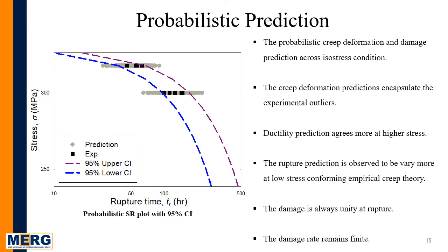Creep deformation, damage evolution, and stress rupture predictions are shown in this slide. The creep deformation prediction encapsulates the experimental outliers across isostress conditions. The ductility prediction seems to agree more at the higher stress, while the rupture prediction is observed to vary more at the lower stress regime, conforming to the empirical creep theory. The damage is always unity at rupture, while the damage rate remains finite at rupture. The stress rupture prediction shows the prediction encapsulating the experimental outer bounds, while the 95% upper and lower confidence bounds are shown. And the confidence bounds seem to be expanding at the lower stress regime.